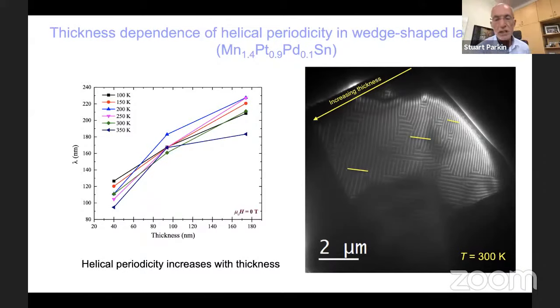So in Lorentz microscopy, we're limited to thicknesses of the material through which this electron beam can be transmitted. And so here we have shown the thickness of a lamella, again formed from this manganese 2 platinum tin compound, where the thickness varies from 40 nanometers to 200 nanometers, approximately. And the period of the helix, which you can see on the right-hand side in this beautiful Lorentz micrograph, also evolves. You can see it's smaller on the right side, and it's wider on the left side. And it changes from 100 to 200 nanometers. So a dramatic change with thickness. But actually, that's at room temperature.